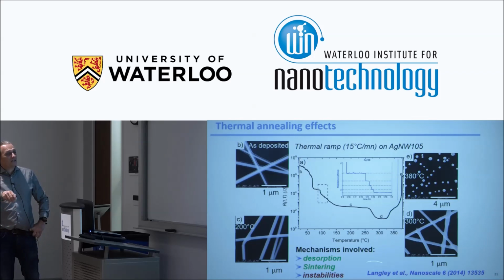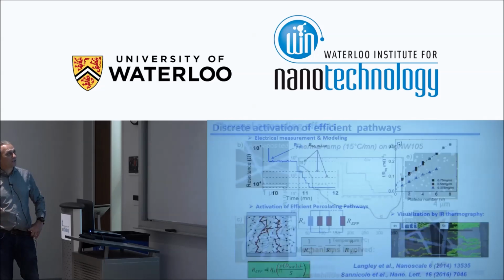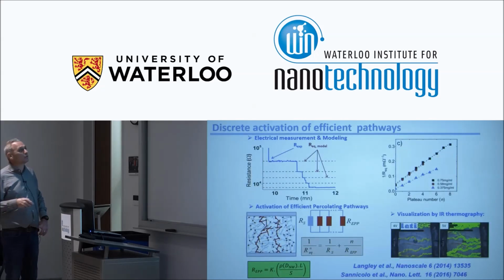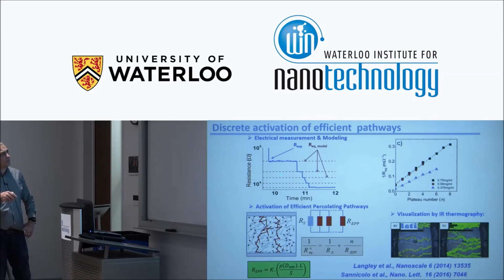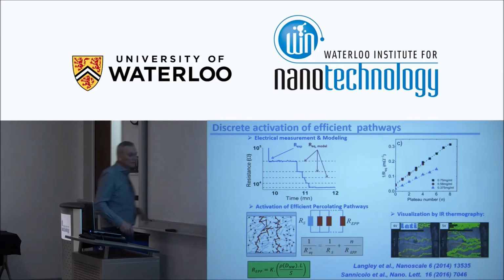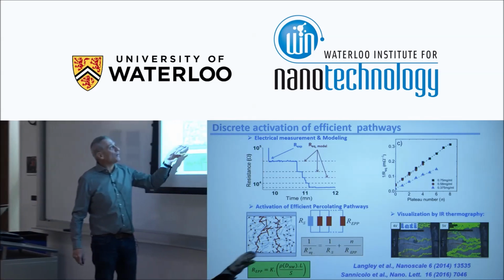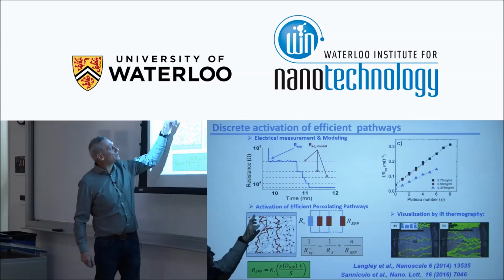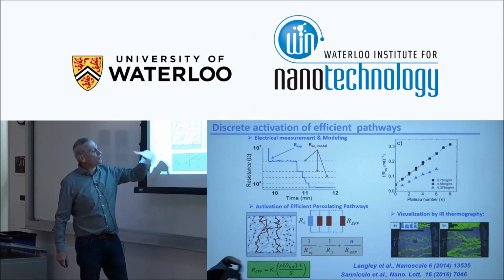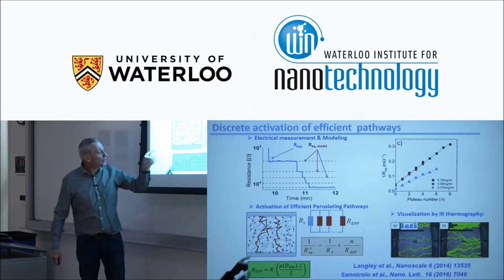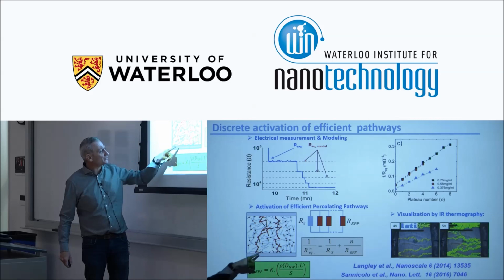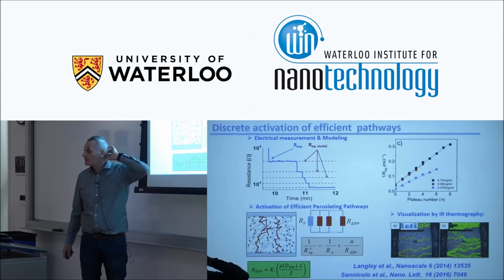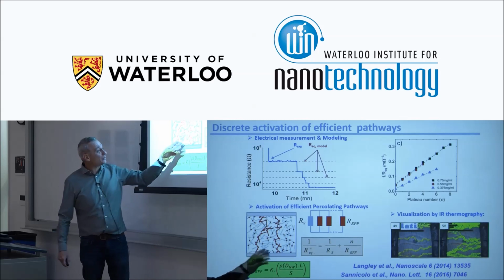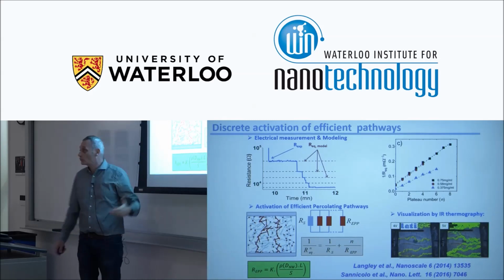And with Daniel Langley, who was a PhD student coming from Australia, we did a small model. This is again resistance versus time at a given temperature, let's say 120 degrees, and we can see some steps when we wait a bit. And then we thought that a schematic way to represent the transport between the electrodes could be like this. We have two electrodes at both sides, and when we are heating the network a bit, some junctions become more and more efficient, in red for example, and suddenly we can have what we call an efficient percolating pathway. And then if we wait a bit longer, there will be another one, okay? And they are supposed to work in parallel.